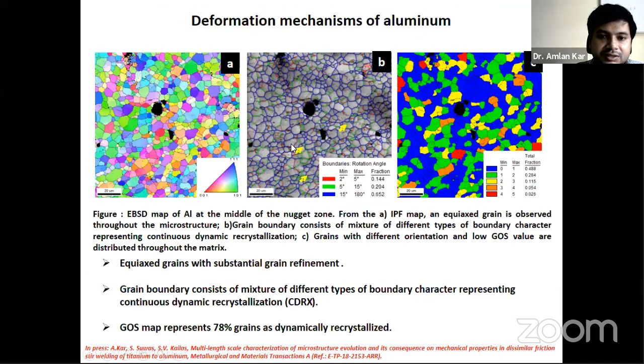So you can see there is an increase in the grain boundary angle from low to higher, and this is the process by which the grains have formed. You can see a few grains, low angle, then sub grain, then low angle grain boundary, then leading to the high angle grain boundary. So these are the typical features of the continuous dynamic recrystallization phenomenon. Since aluminum has a higher number of slip systems and higher stacking fault energy, this is a common phenomenon, recovery and recrystallization based microstructural evolution. And we can see from the GOS map, where the 0 to 2 degree orientation deviation grains actually represent the dynamically recrystallized grains, and from this micrograph you can see 78% of grains are dynamically recrystallized.